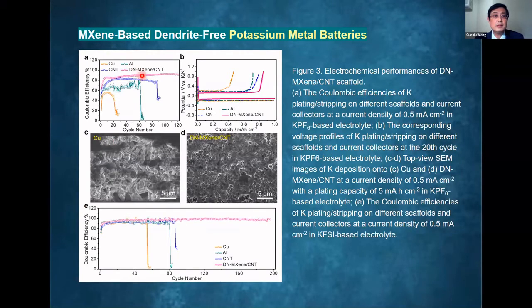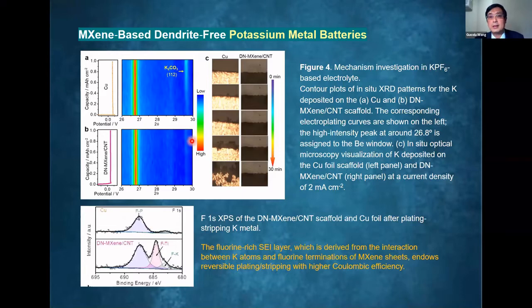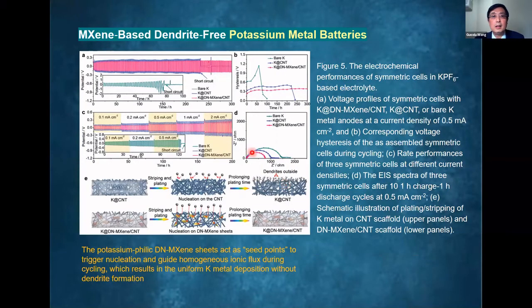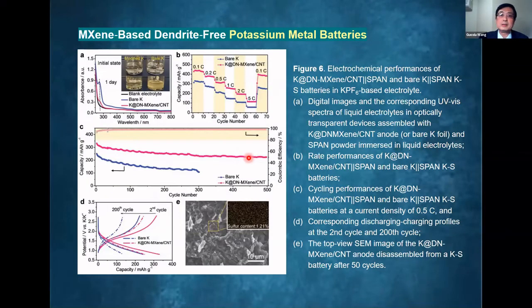And this is the electrochemical performance. You can see the MXene matrix can extend the cycle life of the potassium electrode, and other matrices like copper and aluminum or carbon nanotube gradually failed. And also we did the in situ XRD characterization and also the optical observation. You can see when you use copper, you substantially grew potassium dendrites, but when you use MXene as the substrate, no dendrite grows. So then we use the MXene potassium metal electrode. We construct potassium sulfur batteries, and also we achieved very nice electrochemical performance.